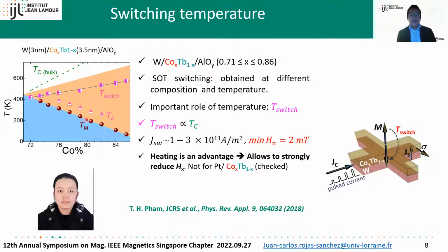Independently, we can measure the magnetic compensation temperature, and we can calculate the angular compensation temperature. We can see that the switching temperature increases when we increase the cobalt concentration. That means that the switching temperature scales more with the Curie temperature. And all the values of the current density for the switching are typical values in heavy metal ferromagnetic bilayers. But we need only a very small in-plane field for the switching of this system, which is very robust.